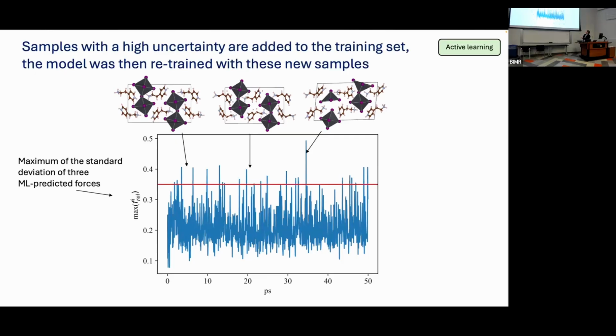And as you evolve through time, eventually the models, this is the forces. And again, the forces are predicted for all elements in the unit cell. There are 3 forces. And we take the difference between the forces on each atom. And we look at where the models disagree. And here the disagreement is very, very large. And that's our estimate for uncertainty. So if the neural networks that have been trained make very different predictions for the same forces, then we call that a highly uncertain sample.